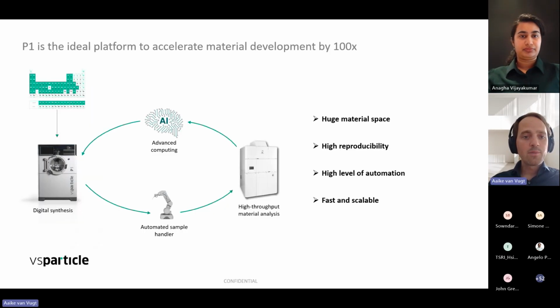Last, I would like to mention that the printer is being analyzed by some of the top groups, both in Europe and the US, including the Caltech group, to evaluate as a next step material synthesis for high throughput self-driving lab applications. Again, because of the huge material space and all the inline quality control, we have very high reproducibility, much higher than any wet chemical method, and a high level of automation, because we are not limited by chemistry. So if you want to change the elemental ratio between two materials, you can just change the frequencies of the two sources. It's not a matter of chemistry, whether or not it will work. And it's very fast and scalable.